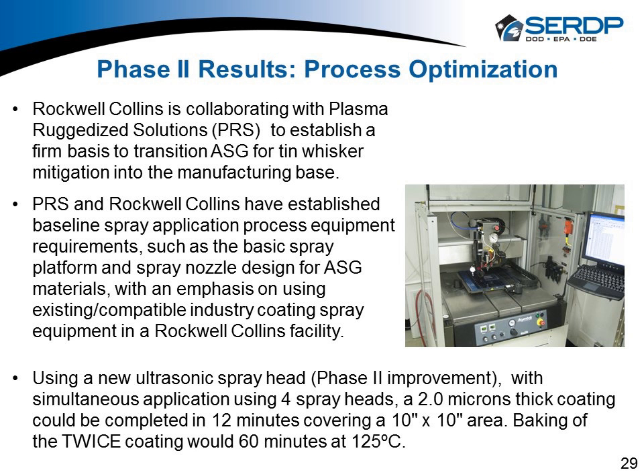If I go to slide 29, again in phase 2, working with PRS and looking at the new ultrasonic head, we're able to do some process improvements. So if you had the conventional machine that a lot of people have in the industry, and you put 4 heads on that and you wanted to spray a 2-micron thick coating, we could cover a 10 by 10 board in 12 minutes. And then, of course, it's going to be another 60 minutes to bake off the twice coating at 125 degrees C. So we were pleased with that because one of my goals was to make sure I'm in line with other conventional coating cycle times.